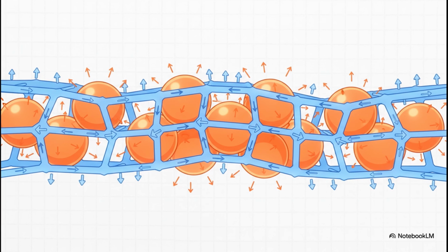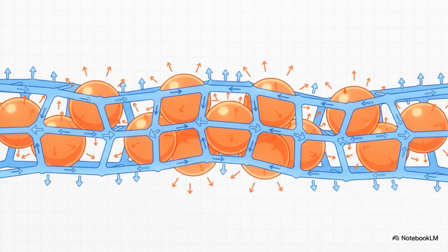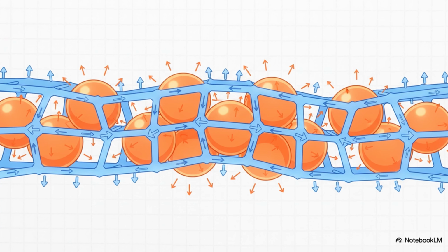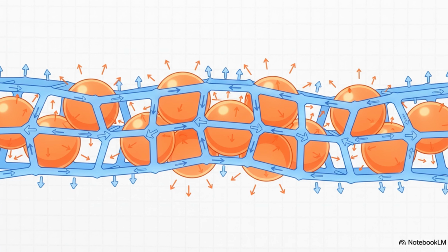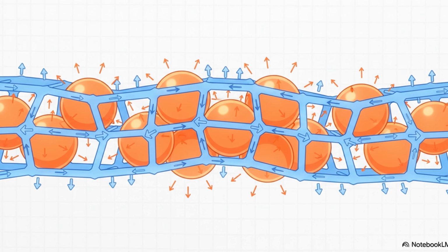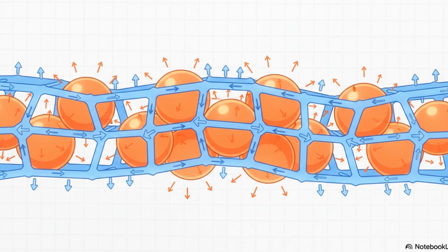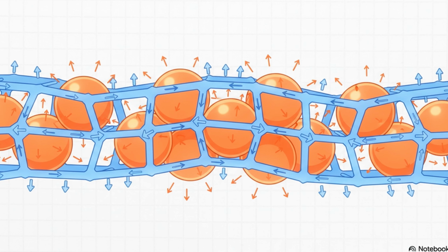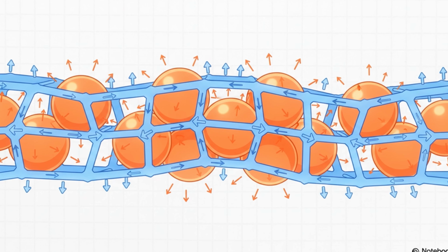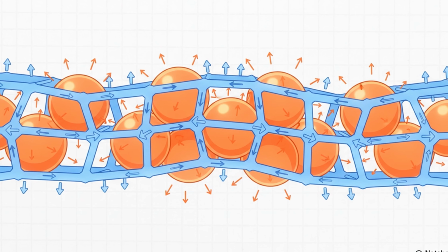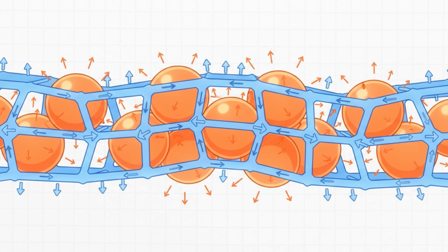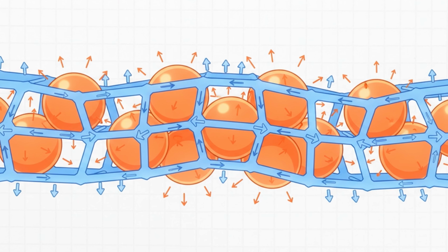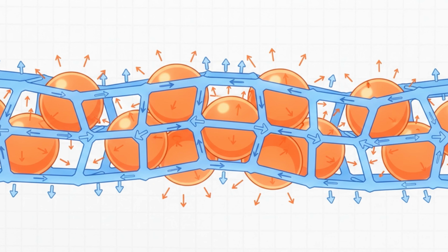So here's the payoff. As the glass starts to cool down, its atomic structure naturally wants to shrink and get tighter. But those bigger potassium ions are now wedged into spaces that are way too small for them. They push back, they resist that contraction, and by pushing outward, they create that immense layer of compressive stress we've been talking about. That's our atomic armor.